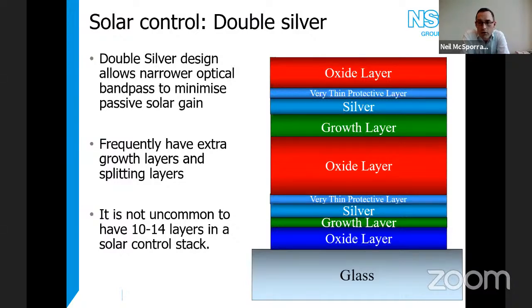Typically, for example, in the UK, regular low emissivity coatings are quite popular. Put them down on glass in a double glazed unit, that would go on the third surface. It allows some passive solar energy to enter and the heat in the room to stay in the room. But of course, in hotter climates, we need solar control coatings. There we have what we call double silver coatings. And they're designed to basically maximize the visible light transmission and minimize the near infrared and UV transmission.